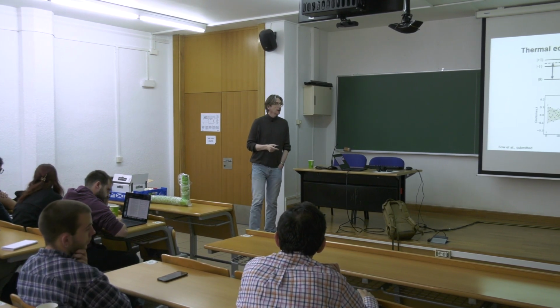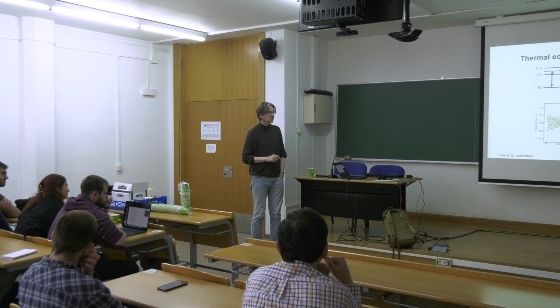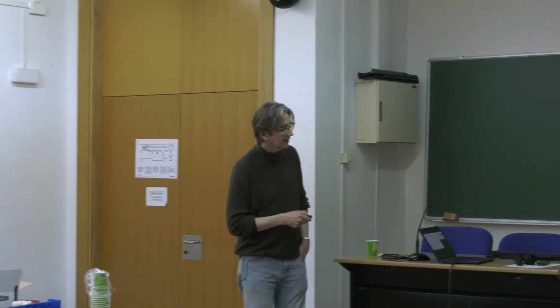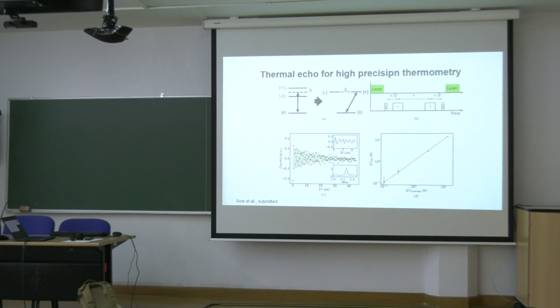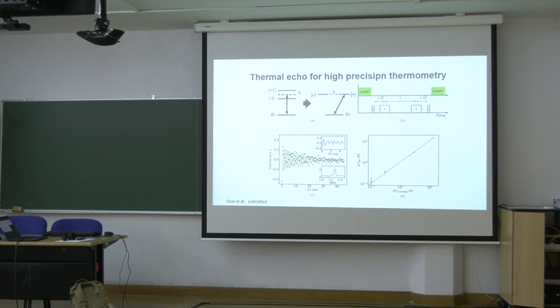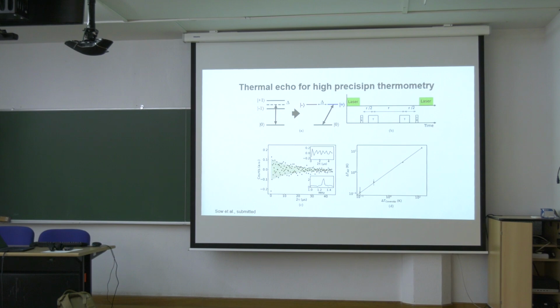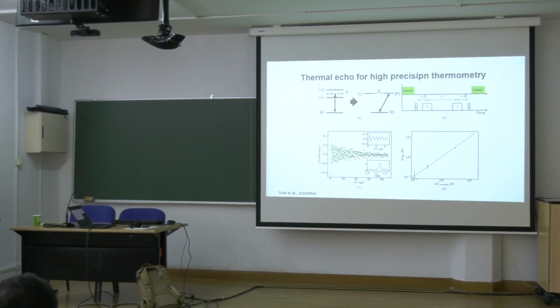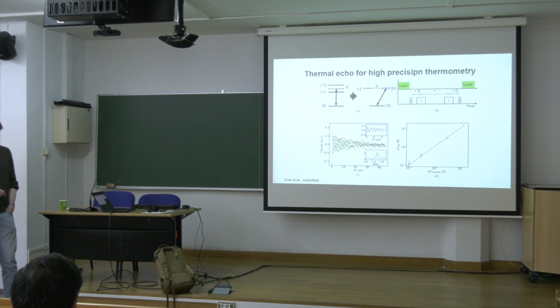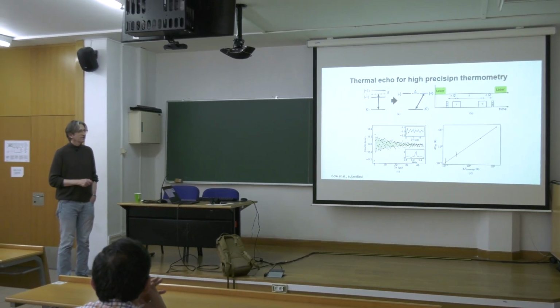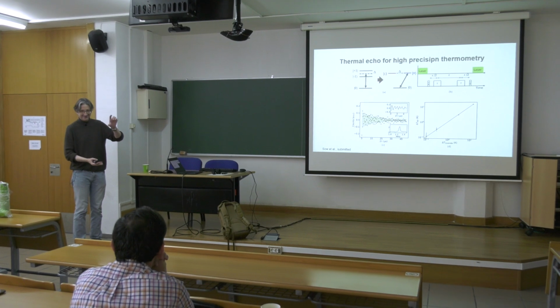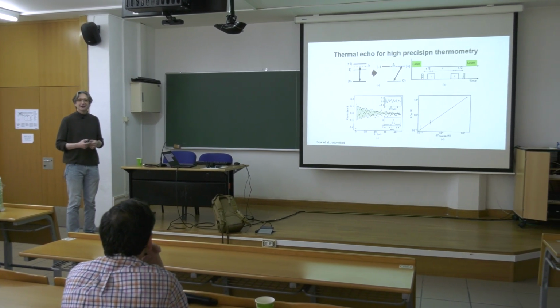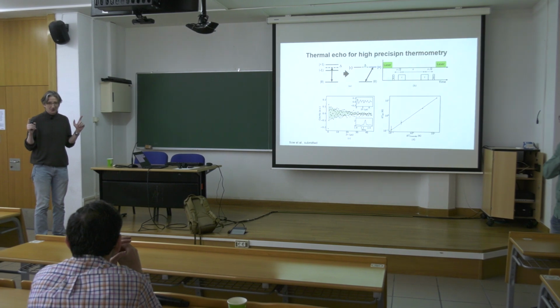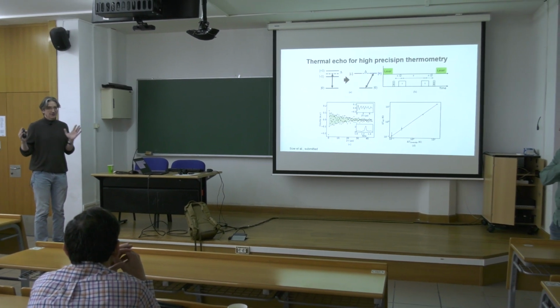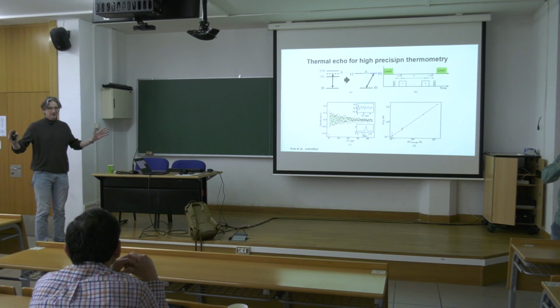Absolutely, that's very important. Fortunately, the effect of temperature and magnetic field can be decoupled, as kind of orthogonal effects. The magnetic field creates a splitting between -1 and +1, but symmetrical. So they're basically moving apart, but the center between them doesn't move. That creates this delta here. But temperature shifts -1 and +1 both together. So if you measure two frequencies at the same time, you can discriminate the effect of temperature, when they move in one direction, and the effect of magnetic field, which creates the splitting.